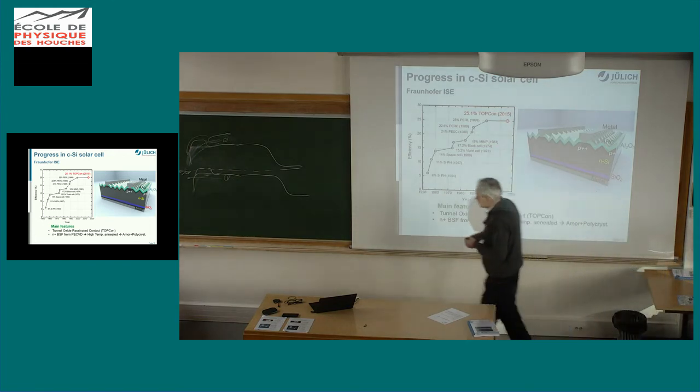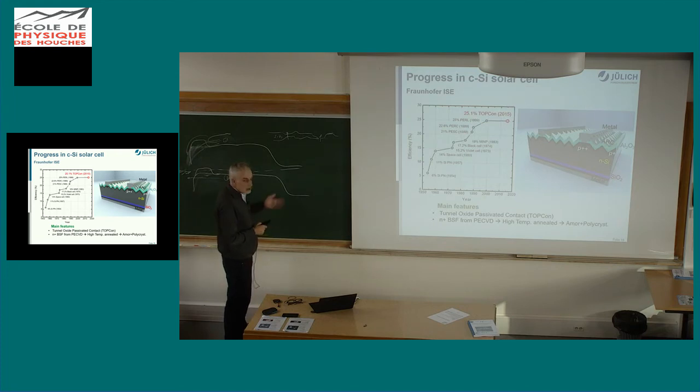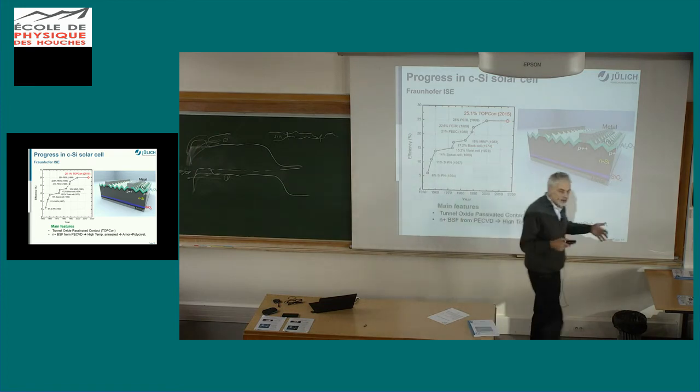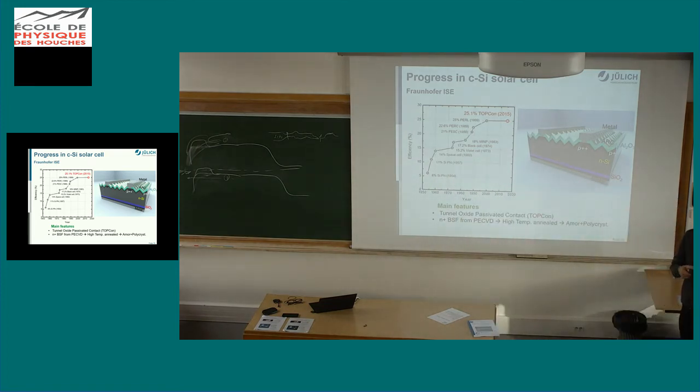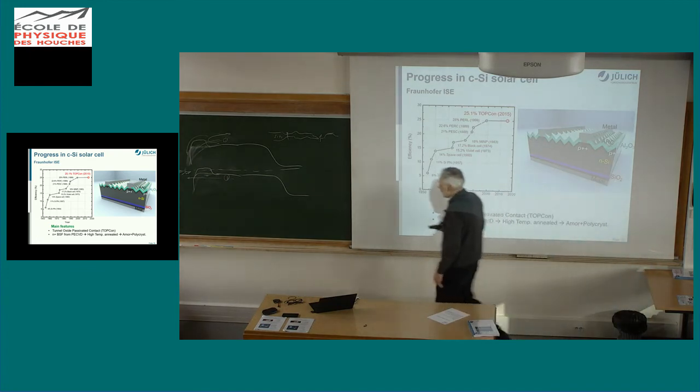So in principle it's believed that you have the silicon oxide, which is not really uniform and sometimes also missing. And if the barrier gets even thinner, or it's just not there, the holes can penetrate. So it's not really the perfect physical thing you want to have, but it somehow works at least as well as this compromise with the point contact. The point contact is also a consequence of not having a perfect solution, but by compromising area you can have a kind of workaround.